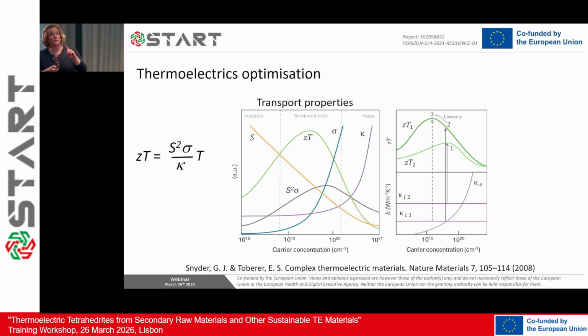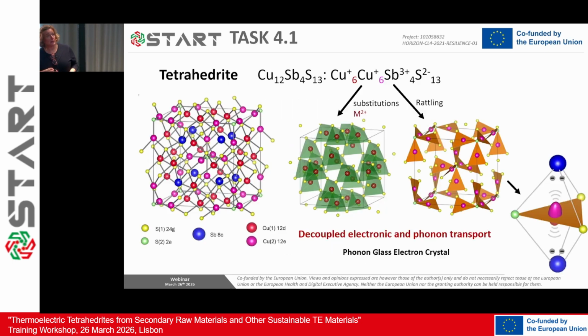By scattering phonons, changing something in the structure so that you can have lower thermal conductivity. But then, and this is very interesting, you need to optimize the Seebeck. So if you lower the carrier concentration, you actually can increase the ZT to an optimal point. So sometimes we like to have a little bit less electrical conductivity than we might think.